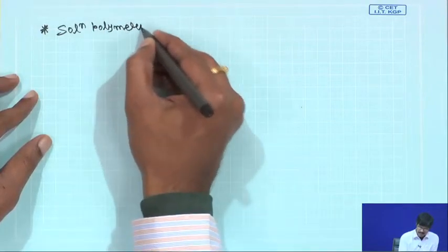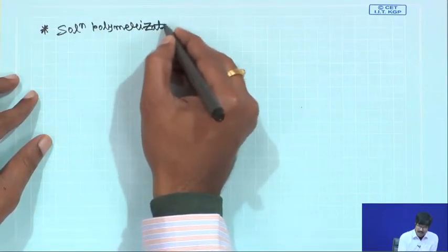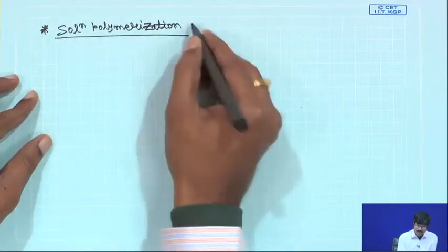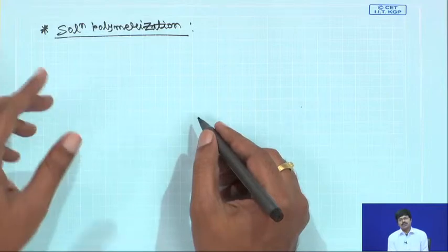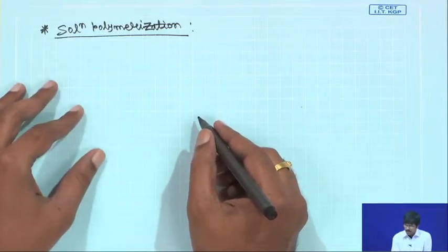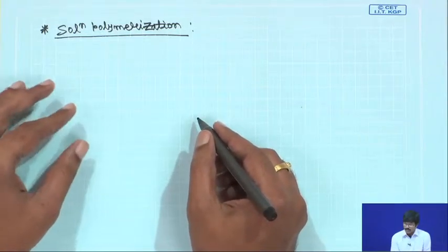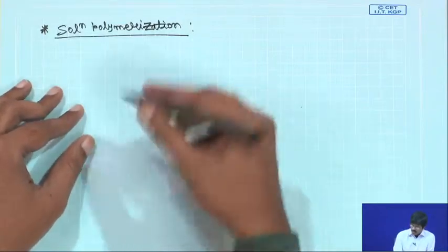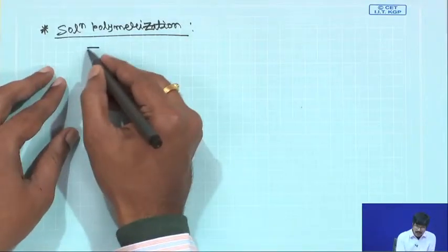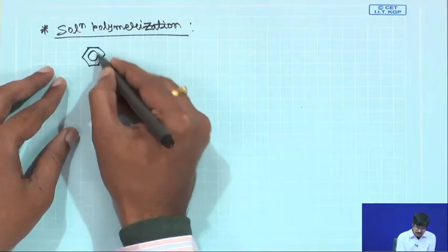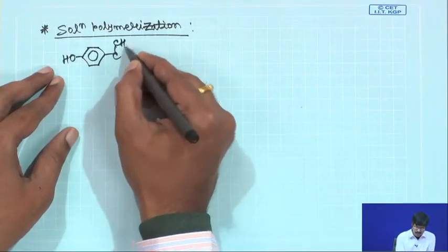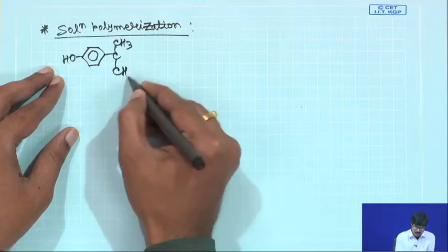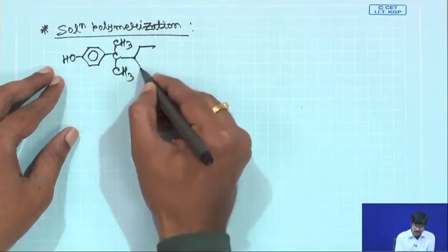polymerization. Basically, this is very similar to your interfacial polycondensation, but here you are not using two solvents, you are basically using only one solvent, which is your organic solvent. So, it is done in one phase, not like in two phase. So, what you do is that you start with your bisphenol A, and of course, in this case it is bisphenol A because you are not using an aqueous solvent in which the solubility is a problem.